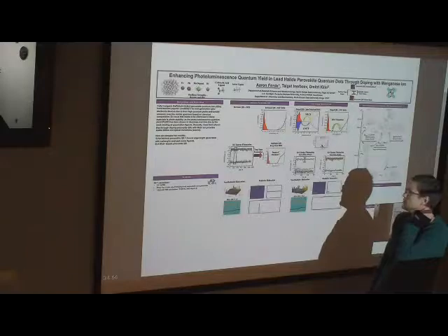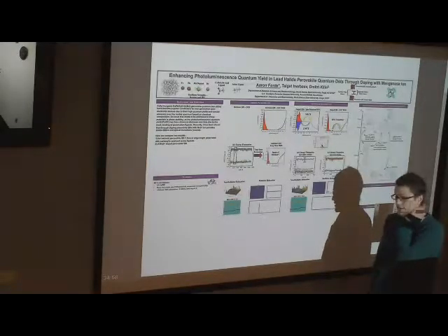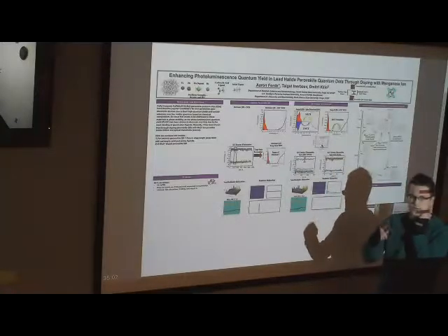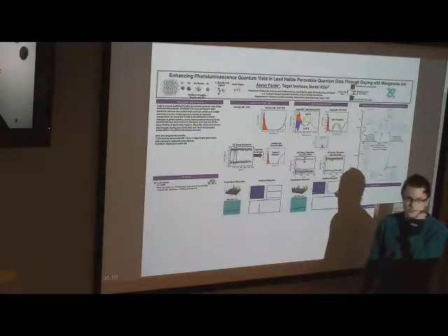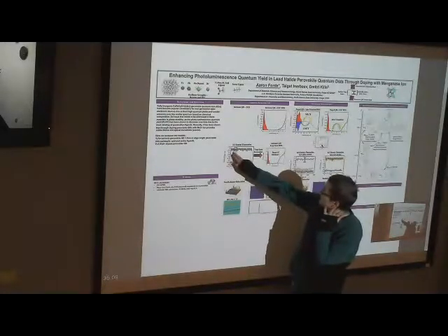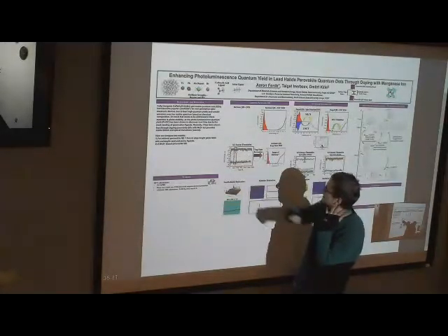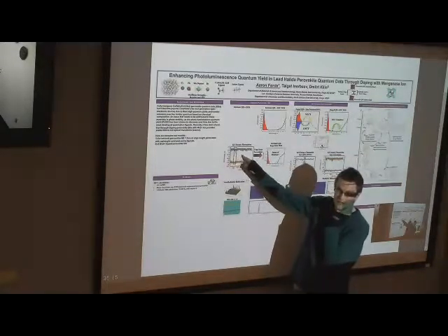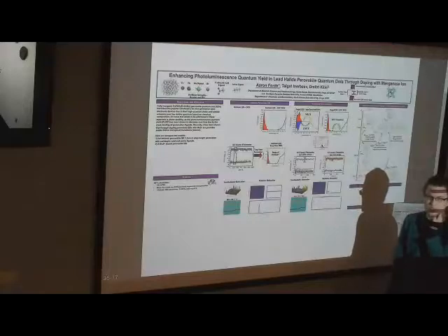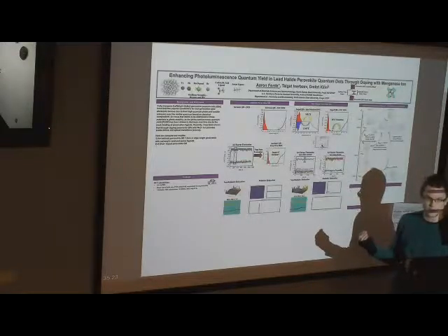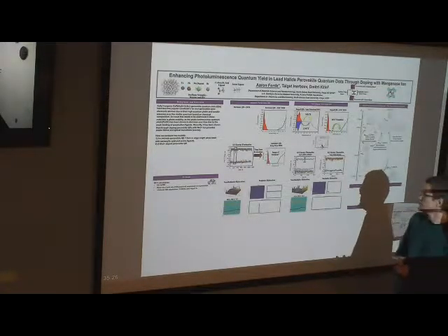And then we moved on to molecular dynamics. By using molecular dynamics, we can track the orbital energies through time as it goes through the steps. And if you look at some of the peaks in the conduction band, you can see that there are states introduced inside the gap, which is usually a clear sign that there's a trap state occurring, or that one or enough ligands come off of the perovskite quantum dot to introduce trap states.